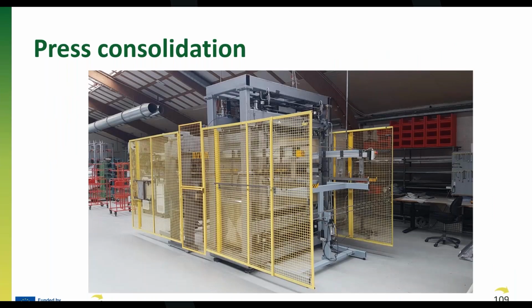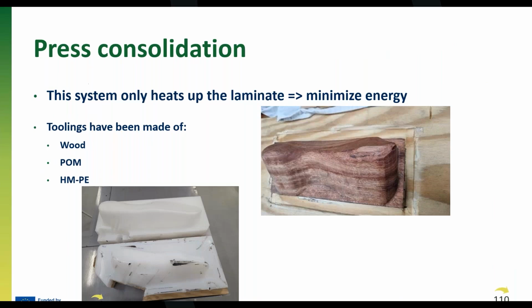Here you actually see the machine as we have designed and been running these trials on, and here it's running from the right hand side to the left hand side. So yeah, next one. So as said, the system only heats up the laminate, which minimizes the energy you have to put in, but also means that here you can make tooling of different materials, and we have been using wood, POM, or high molecular weight polyethylene. So we see those 3 different toolings, and they've been working very well with our materials. So next one.